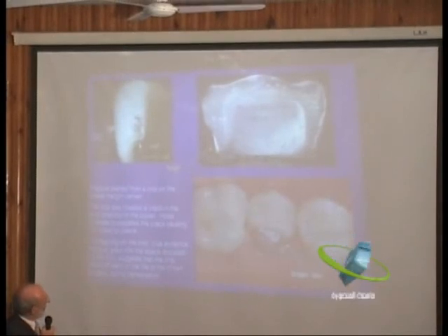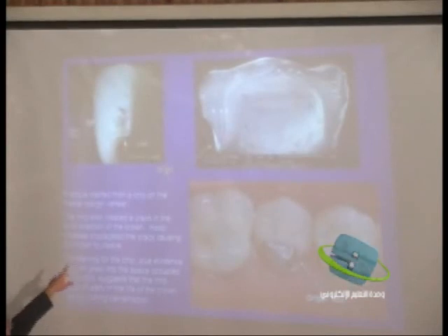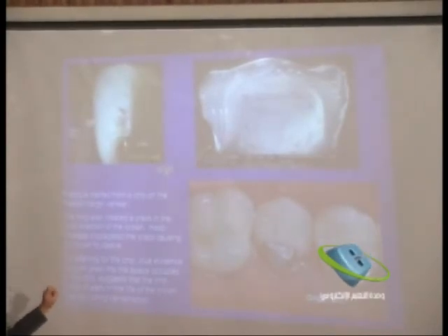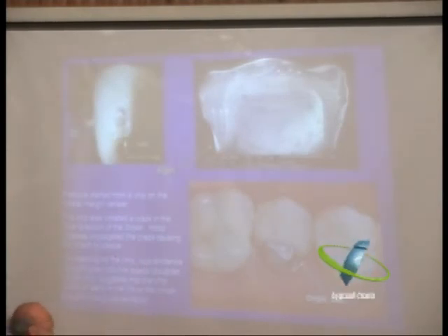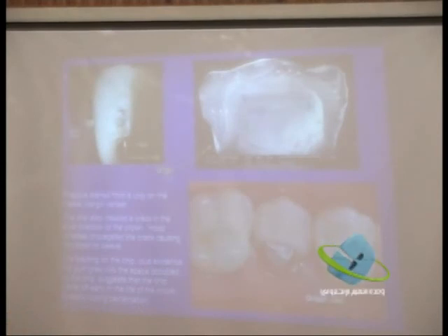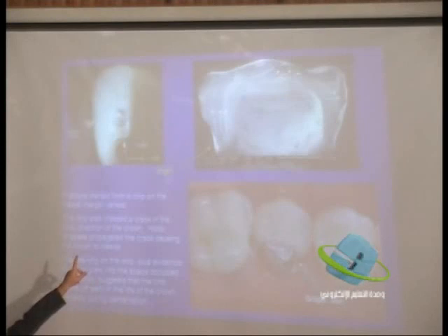And what they noticed was that there was a small little chip that had been placed during the initial placement, as though the porcelain on the outer surface had chipped slightly, and you could see now that was a much narrower region around the margin of that system. That thin margin, now under the loading stresses and what we call hoop stresses, these are like the stresses in a drum. If it's under pressure, that can initiate the crack, and then over the course of time that crack grew up and across, and that material completely failed.